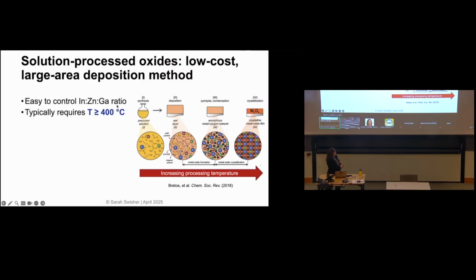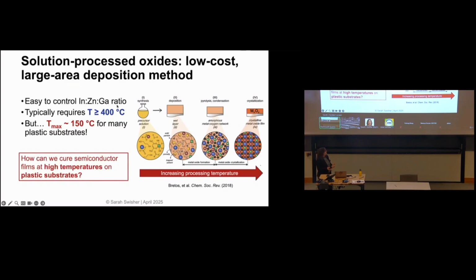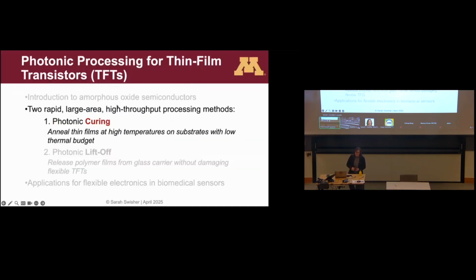The problem is that this conversion to make these precursors turn into the semiconductor material typically happens at a pretty high temperature, about 400 degrees. And the maximum temperature that we can use for plastics, remember we want to put this on a flexible plastic substrate, the maximum temperature there is about 150 degrees. So here's the question. What can we do so that we can cure a semiconductor at a relatively high temperature, right? This is still lower than crystalline semiconductors like silicon or the crystalline IGZO. But how can we do this so that we can reach this temperature of 400 or 500 degrees without damaging that plastic substrate? So in my group, we've been working with this process that we call photonic curing.